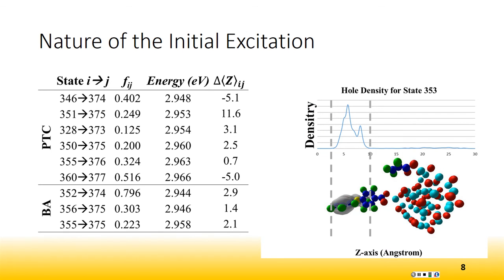So then this is just a partial charge density of the highest charge transfer state. So this is 353, and we can see that the charge transfer is only on the ligand, and there's no localization of the hole on the quantum dot.